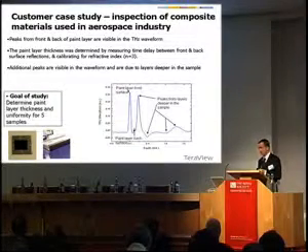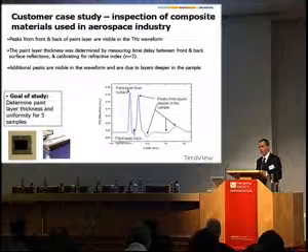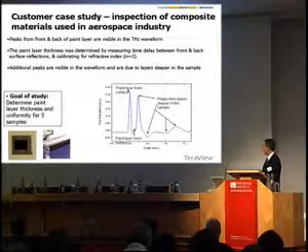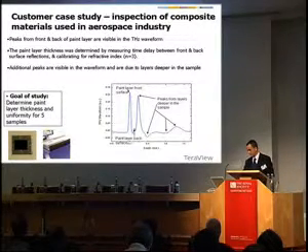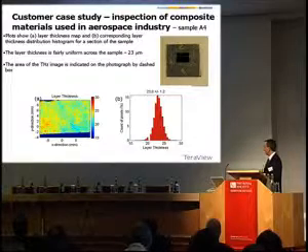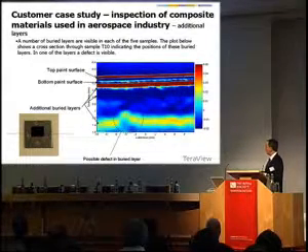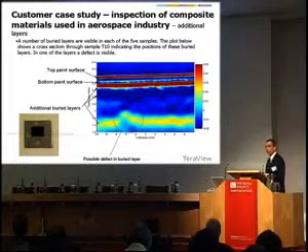Moving on to composite materials — this particular one was from the aerospace industry — again the question was could we use terahertz to image and detect any issues buried in the inner layers. Here we're seeing peaks and troughs corresponding to the interfaces between the various layers. The goal was to determine the thickness and uniformity of the layers. In this sample we can see a fairly uniform layer thickness; however, as we move on, we can see in one of the deeper layers a possible defect — a non-uniformity — at some one to one-and-a-half millimetres into the sample.